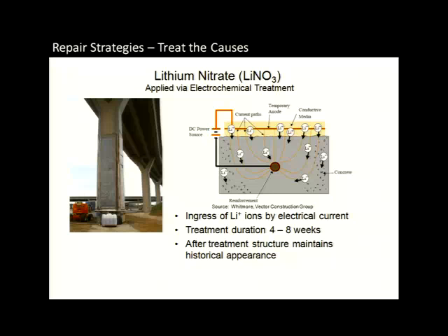So we drilled in, in essence, made Swiss cheese out of the column, not to affect it structurally, but about every 2 feet, drilled in 2 feet of depth into the concrete so that we could tie into the interior rebar and use that as our cathode. And the idea is that we can basically drive lithium ions into the heart of the concrete, and we can draw out a complementary cation. So we would typically be drawing out calcium ions.